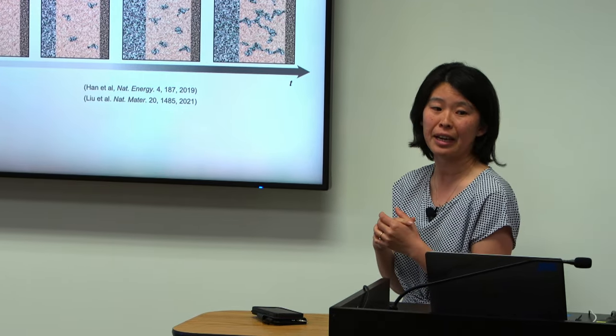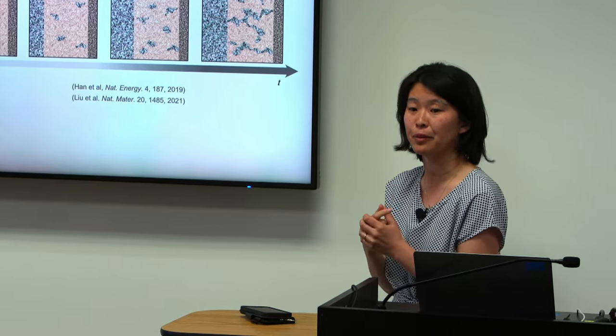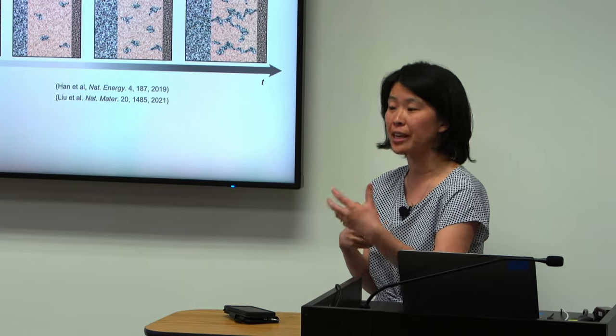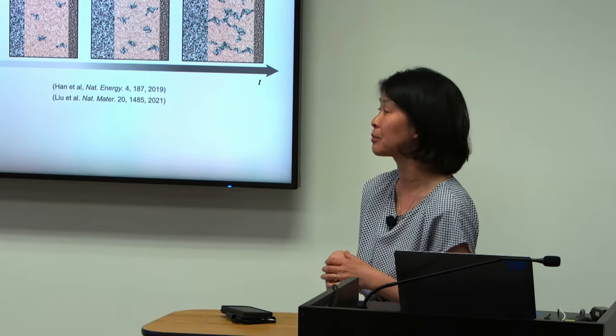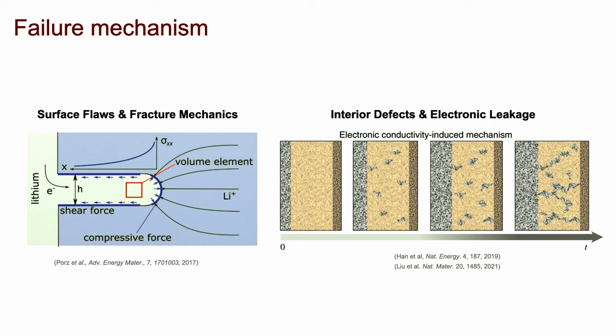So what we're trying to do in the group right now is break down some of the mechanisms behind this and use this as a strategy for figuring out how we can come up with some solutions. On the right here, this is a schematic showing the growth of a lithium dendrite and the formation of a stress field in front of it. This type of argument says that mechanics plays the dominant role, where the pressure that's formed at the tip of the dendrite determines when the material will fracture.